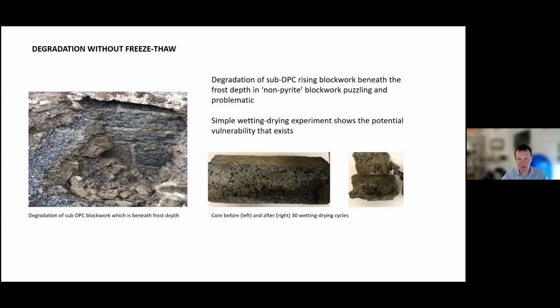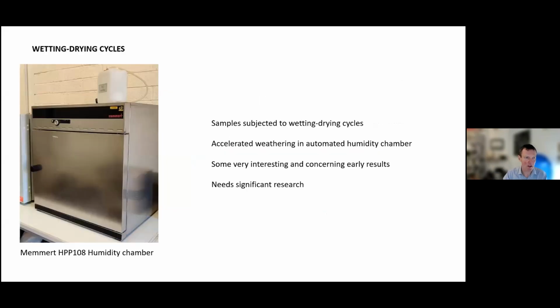and we didn't understand that this degradation could occur. And this has actually been borne out by some experimental wetting drying procedures where you simply put concrete into water, dry it out, in and out, and it can degrade. Certain concrete is not durable in wet and dry. And this is a technique now I want to develop. So this is a humidity chamber where samples will be automatically subjected to wet and drying cycles. So it'll effectively smoke out the problematic materials.